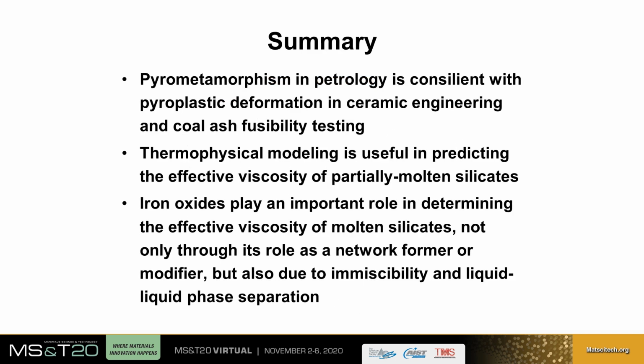To summarize, pyrometamorphism in petrology is consilient with pyroplastic deformation in ceramic engineering and coal ash fusibility testing. Next, thermophysical modeling is useful in predicting the effective viscosity of partially molten silicates. Lastly, iron oxides play an important role in determining the effective viscosity of molten silicates, not only through its role as a network former or modifier, but also due to immiscibility and liquid-liquid phase separation.